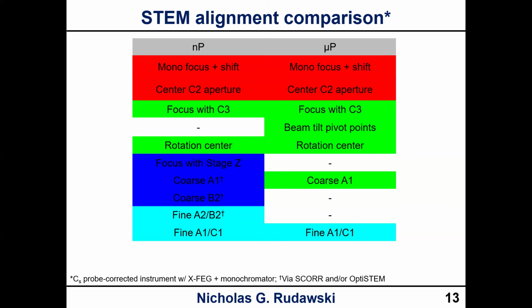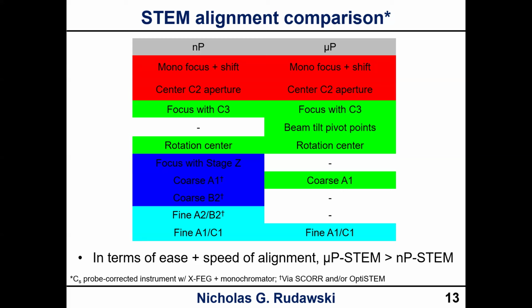In microprobe, though, it's a little bit less complicated. Things are just easier here. The big thing is we don't have to worry so much about dealing with the aberrations. We're not dealing with a situation where we're aberration limited, so things become much more simplified. You notice that there's no steps that really involve STEM mode with diffraction on, which would be where you're looking at the Ronchigram. So in terms of ease of alignment, microprobe-STEM really has an advantage here.